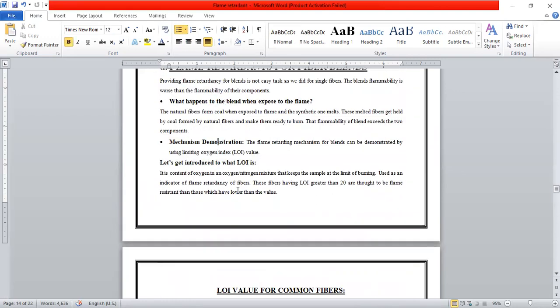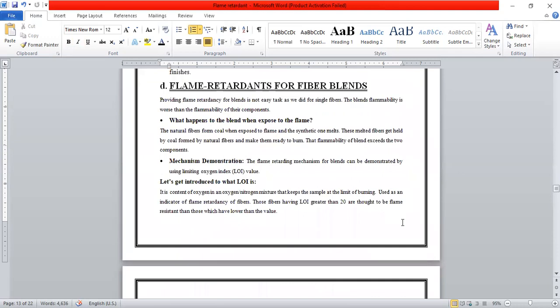Now there are flame retardants for some fiber blends. Providing flame retardancy for blends is not as easy a task as it was for single fibers. The blend's flammability is worse than the flammability of their components. The question arises, what happens to the blend when exposed to flame? The natural fiber forms char when exposed to flame, and the synthetic one melts. The melted fibers get held by the char formed by natural fibers and make them ready to burn. The flammability of the blend exceeds the two components.